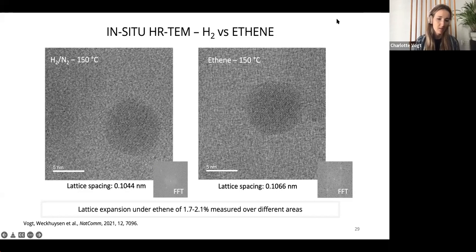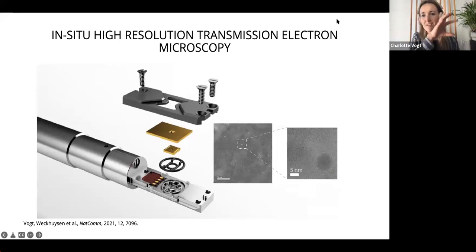My personal preference is not to use colloidal particles or ligand-stabilized particles when I'm studying these types of things. So all of these catalysts were formed by homogeneous deposition precipitation. I didn't make these catalysts; we had somebody who was very experienced. The nickel nanoparticles on the silica that you saw were homogeneous deposition precipitated, and just by tuning the parameters of the onset of the nucleation of both the salt and the support, we were able to obtain these different nanoparticle sizes.